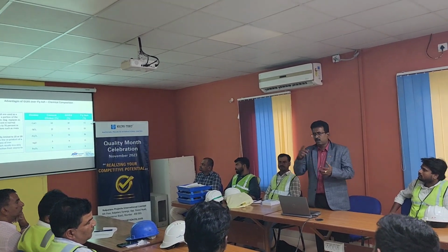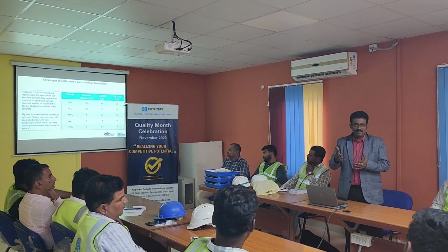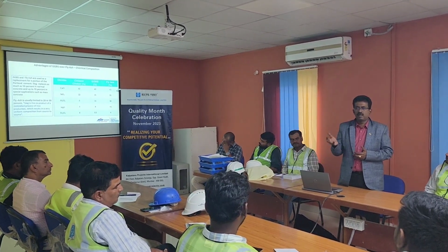You need a certain reaction; a one-day reaction will trigger the GGBS to react. I told you secondary hydration will start after 10 hours only, so you are not losing. When you look at fly ash, it has pozzolanic activity. The activity will start after 5 to 6 or 7 days. The cement has to completely hydrate for the pozzolanic properties to start. Whereas GGBS starts reacting after 10 hours only, along with the calcium hydroxide. It reacts with the calcium ion. That is the beauty of GGBS compared to fly ash.